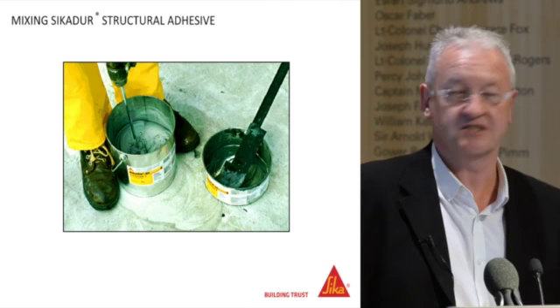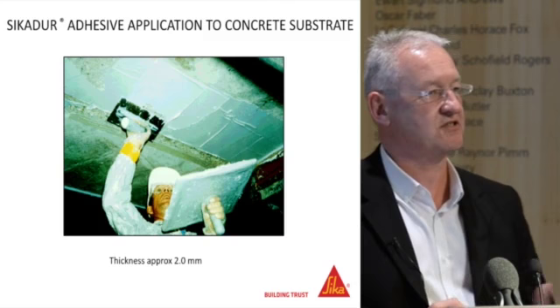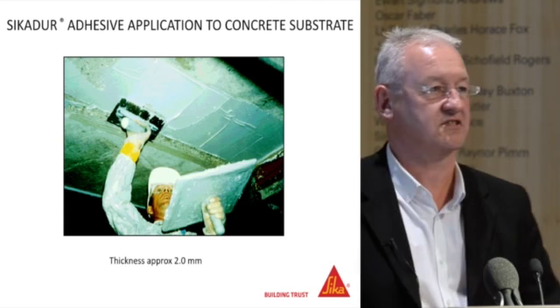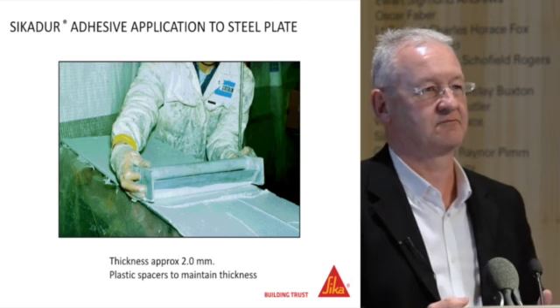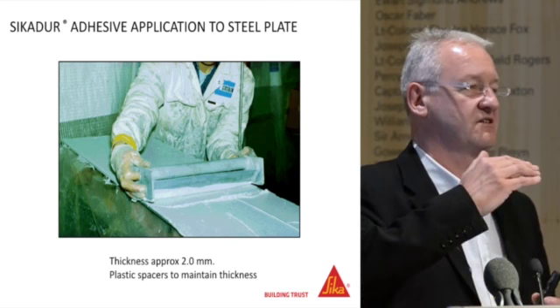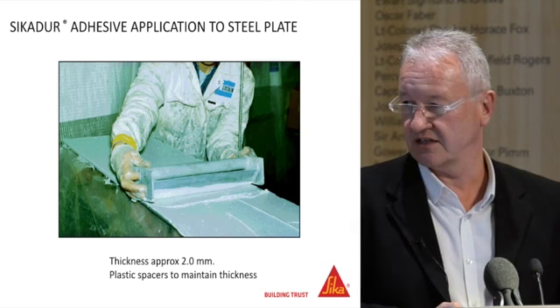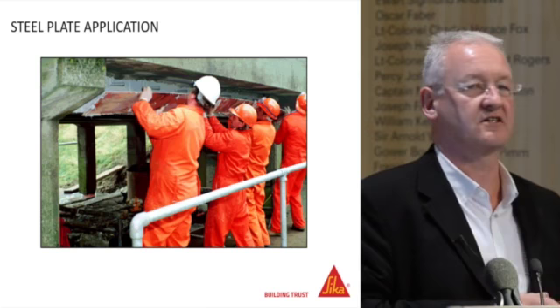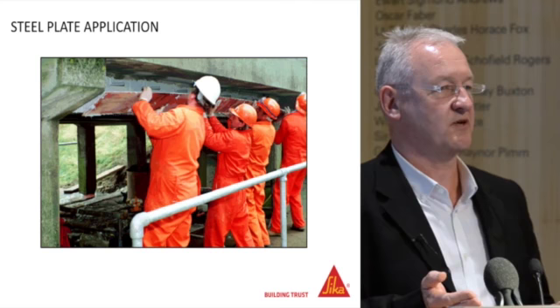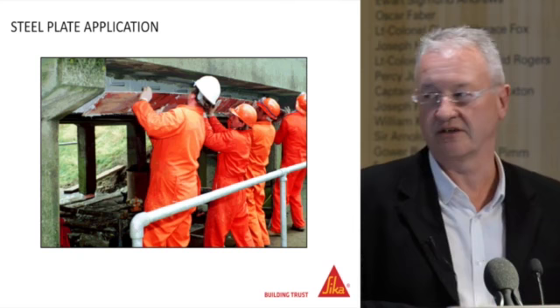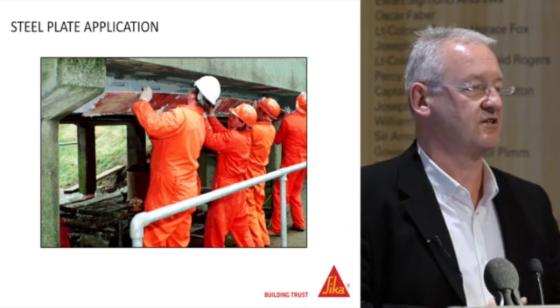Plates are wrapped in fabric or plastic for protection and brought to site. The plastic wrappings are removed, a final degrease is done on the coating on the bond line, and then the products are mixed together. You can see the grey and black components — when mixed they form a slightly darker grey. If not fully mixed you can see the dark hardener still present, so you continue mixing until it's fully homogeneous. The adhesive is applied around 2 mm to the concrete and 2 mm to the steel plate, giving a bond line of around 3–4 mm.